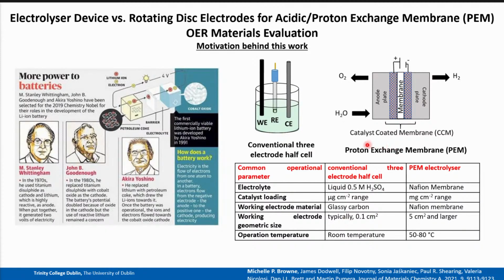Then for the actual proton exchange membrane devices, the working electrode material is the Nafion membrane, and I will show you what I mean by this, the working electrodes, on the next 2 slides. Then the different geometric sizes also completely differ, and even the temperature that these 2 devices are operated at is significantly different. So for the 3-electrode cell, it's room temperature, and then for the proton exchange membrane device, it's between about 50 to 80 degrees. And this will significantly change the kinetics of your materials.